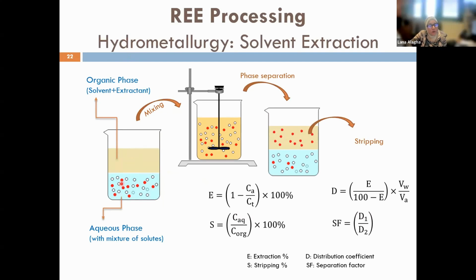But usually you mix your aqueous phase that has, let's say, your rare earth elements with an organic phase that has extractant that is selective for rare earth, and then you do the phase separation. In this case, your rare earth will complex with the extractant molecule and move to the organic phase, and then you can separate the phases. Now your rare earth is in the organic phase, and you take the organic phase and mix it with what we call stripping solution, which is an aqueous solution of a specific acidity, and then you strip the rare earth compound back to aqueous phase. In this case, you have a pure or almost pure solution of rare earth compounds.